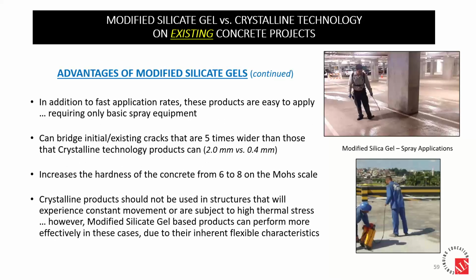So in addition to being fast and easy to apply, the equipment is very, very simple. You don't have expensive, elaborate equipment required to apply a silicate gel strategy. And another big advantage is both of these strategies will heal cracks as they start to form in the future. So I mentioned the chemicals stay behind and are activated by water. So let's say we've waterproofed a concrete structure and 5 years later a crack begins to develop. As soon as water is present, up to 0.4 millimeters, these materials will fill that crack and continue to waterproof.